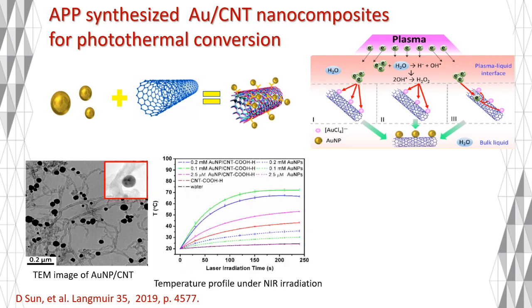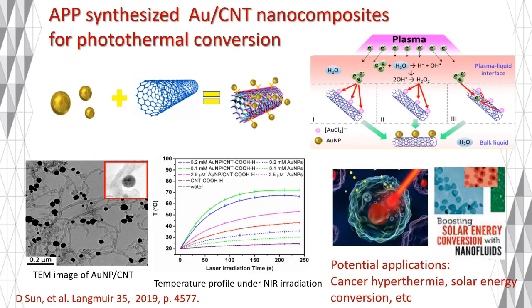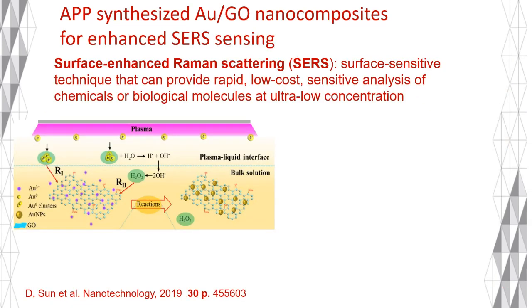Moreover, we demonstrated that this hybrid material exhibits a significantly enhanced photothermal conversion effect compared to either pure gold nanoparticles or pure CNTs. That is, when we exposed our sample to a near-infrared laser, the hybrid material can efficiently absorb the light and convert it into heat, resulting in a rapid increase in temperature to above 45 degrees C in about 40 seconds. This property makes the hybrid material highly suitable for potential applications such as minimally invasive cancer hyperthermia therapy or for solar energy conversion. We are delighted that our pioneering research showcased the potential of APP plasma technology for creating novel composite materials. And my team is excited to extend this versatile platform technology to a broader range of materials.